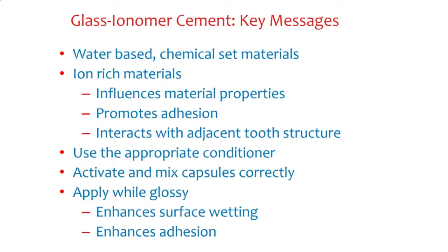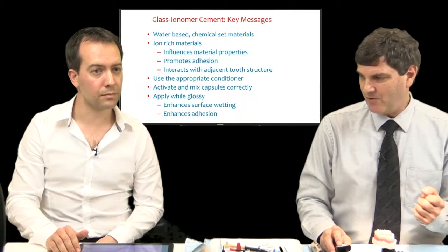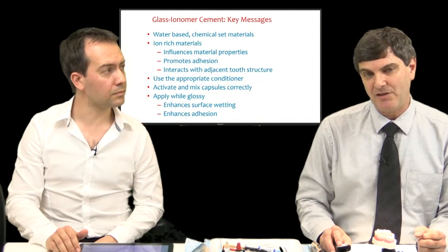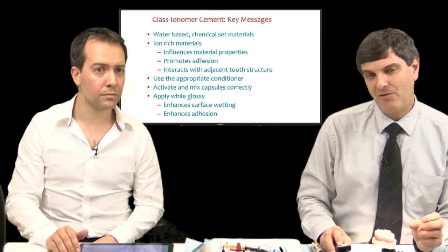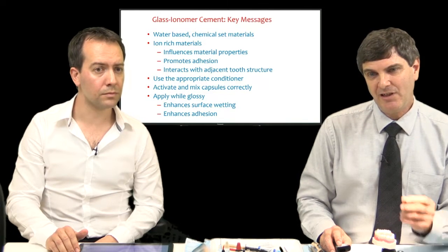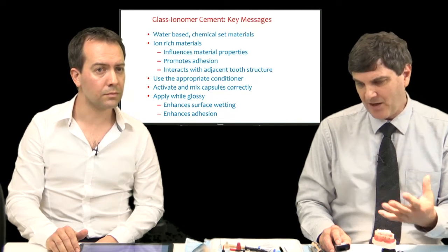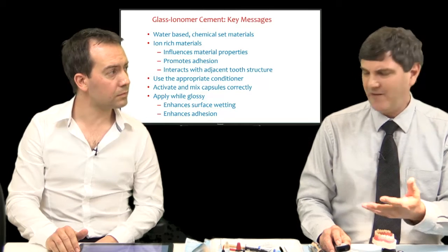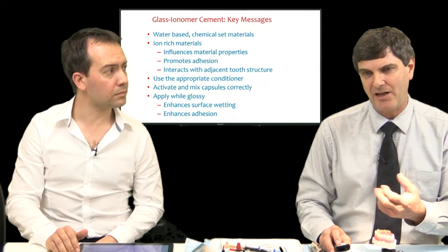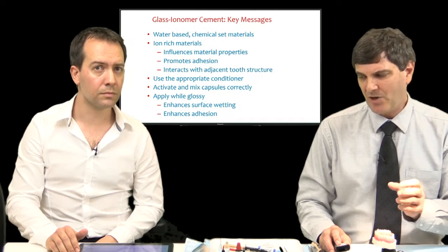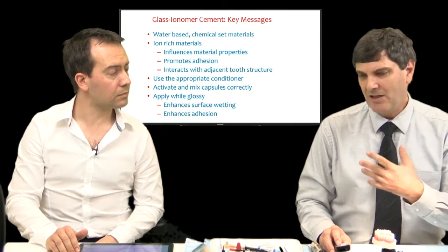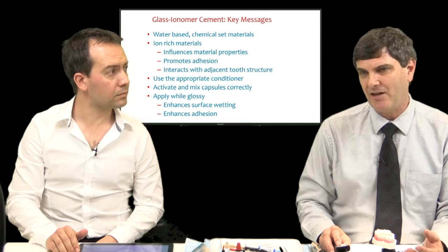And probably the most important thing to me is that as an adhesive material, they're most effective when they're still in their active state. In other words, where you've still got some of that liquid reaction available to go with the tooth structure. And you can tell that with the glass ionomers because they're quite glossy when they're first mixed. Once they lose that glossy surface and they go a bit putty-like and dry looking on the surface, they're not going to interact with tooth surfaces, so you're going to lose a lot of that adhesive ability. So I always make sure that when I'm placing my glass ionomers, they're still fluid, they're still glossy in appearance, to maximise that adhesion to the tooth structure.